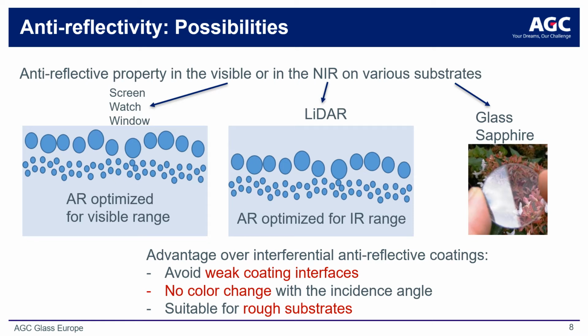Secondly, anti-reflective treatment by ion implantation allows a much more robust and abrasion-resistant solution. This enables applications with rough substrates or those used in environmentally aggressive conditions to be readily used. AR coatings by ion implantation can be optimized for specific spectral ranges like the visible for display applications or in the near infrared, for example for LiDAR applications. The process can be performed on a range of substrate materials like glass, sapphire, and semiconductors.